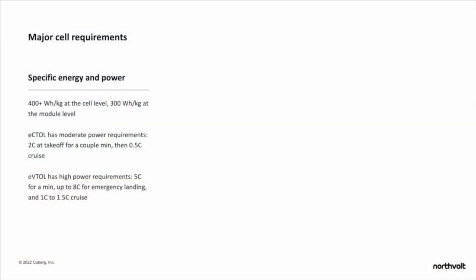So first, looking at cell level requirements for air mobility, I would argue based on what I've heard in the industry that most customers are pretty happy if you can get to roughly 400 watt hours per kilogram at the cell level. Of course, everyone would always want more specific energy. You can never have enough. But what we see is if you get to about 400 at the cell level, 300 at the module level, you're at a point where a lot of the early business models and applications are enabled and can be done with aircraft designs that are currently already in test flights today.